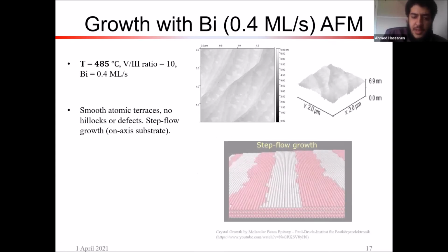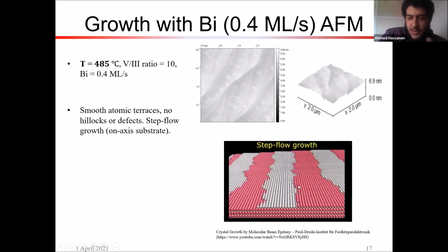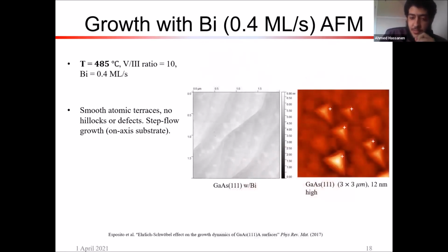And so this is just an animation of how the growth proceeds. And so you can see when we use this, instead of these hillocks, we get this step flow growth. And this really is indicative of how smooth this surface that we're creating is. And so again, just to drive the point home, this is the surface that we got with bismuth, and this is an example surface of gallium arsenide 111 growth, homoepitaxy without bismuth, and we can see clearly the atomic steps here, how uniform it is, versus the hillocks that we're getting, like micrometer level hillocks.